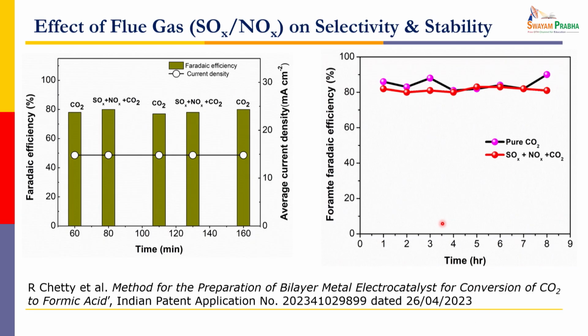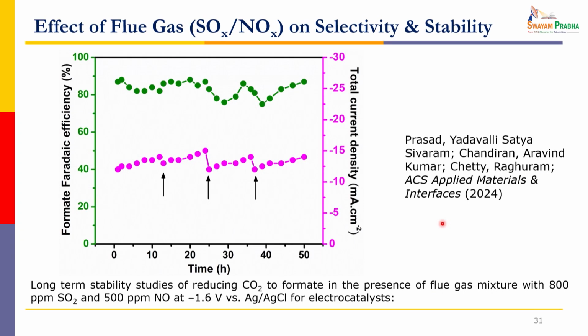And then, just for comparison, we did a stability test, to see how long it can work. If you look at the pure CO2 and the one with CO2 plus NOx and SOx, there was not much difference. They were almost similar, even for 7-8 hours. Initially we started with 8 hours, and later we improved that to close to 50 hours. So this is 50 hours of data.